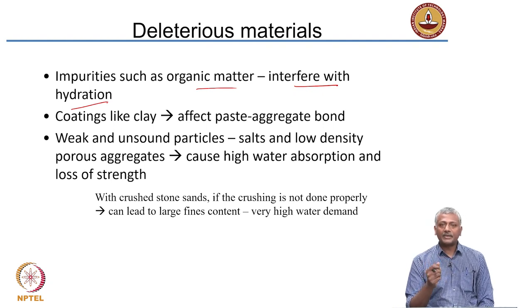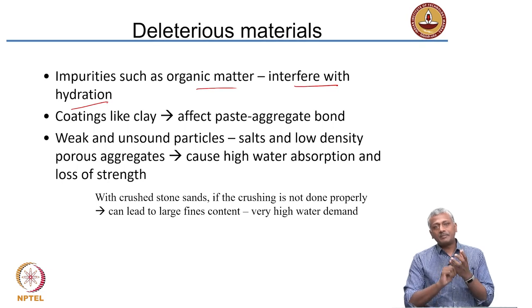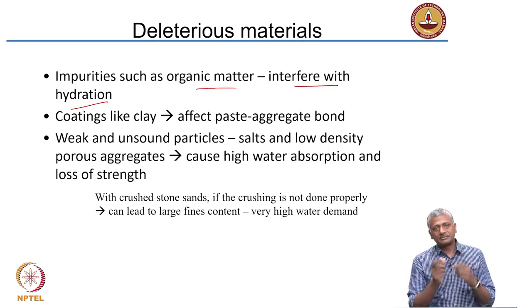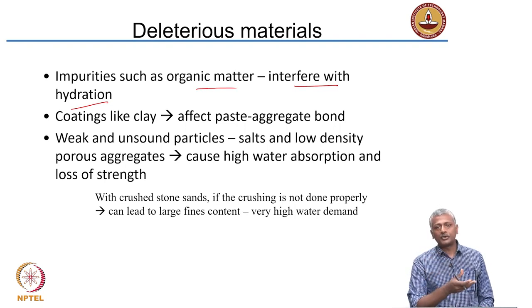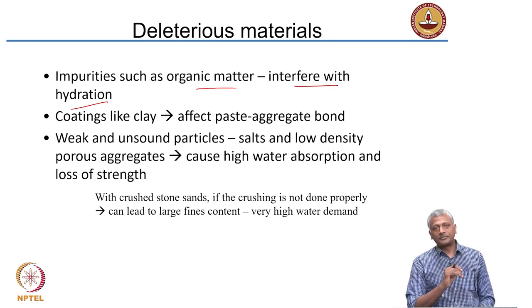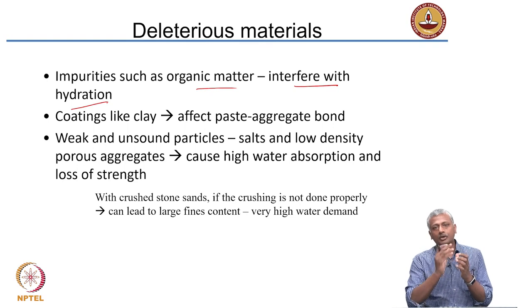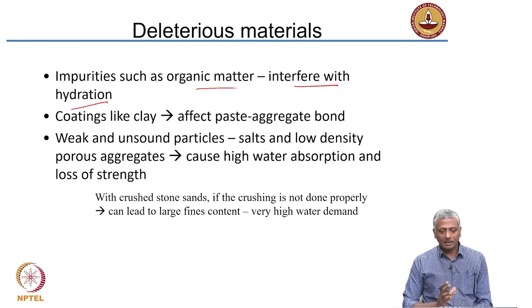When you have clay, it may start forming a lining on the surface of the aggregate. Sometimes aggregate that you get is dirty because of this clay lining. If you do not clean it up well before using it, that will affect the paste-aggregate bond. The paste has to bond well with the aggregate, and if you have a lining of clay on top, it is going to spoil the bond.